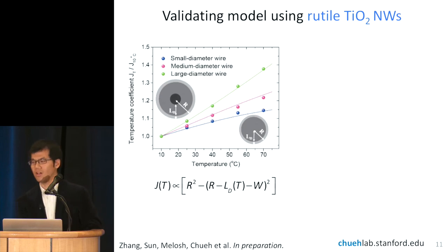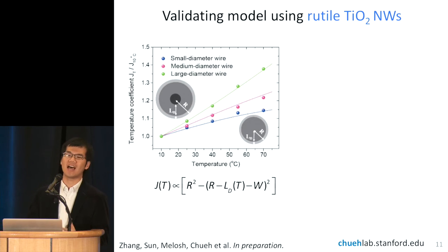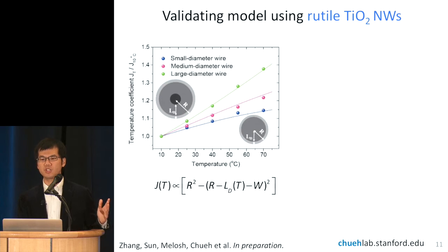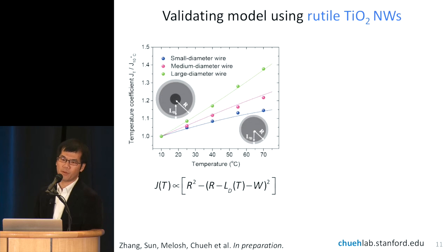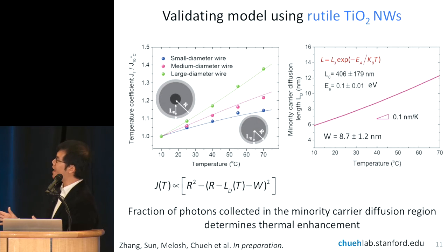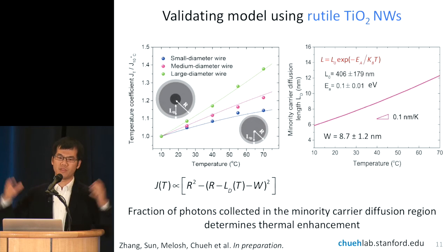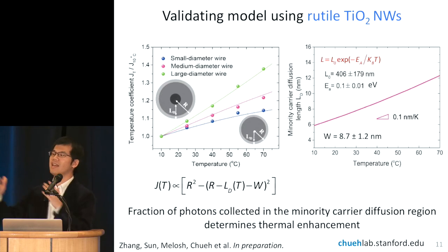But when you have a very small wire, eventually you are activating the entire wire through thermal activation of the minority carrier diffusion length. That's why the blue line tends to plateau. And our model perfectly captures this transition from a linear behavior to a more plateau behavior. And from this data set, which took three samples and about a day to measure, we're actually able to back out the minority carrier diffusion length, the activation energy of minority carrier transport, and also the space charge layer width by using the equation I have down there, just by considering the geometry, the diameter of the wire, the thickness of the space charge region, and the thickness of the minority carrier diffusion. There's a lot of assumption, but we are very happy that such a simple model can explain the data accurately.